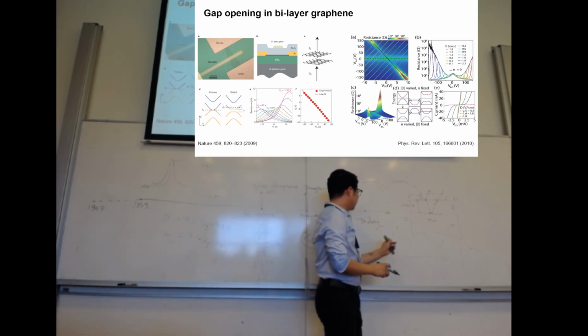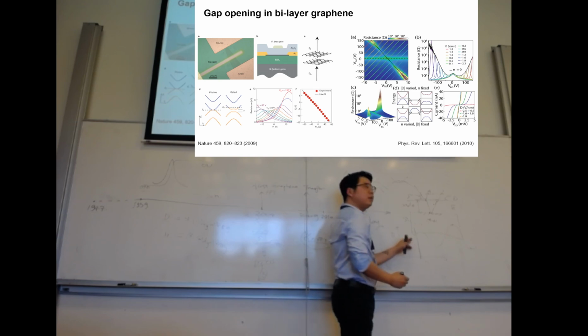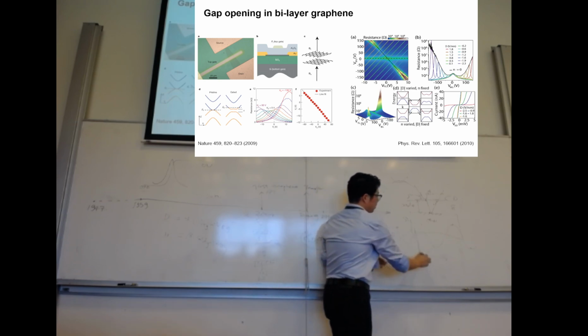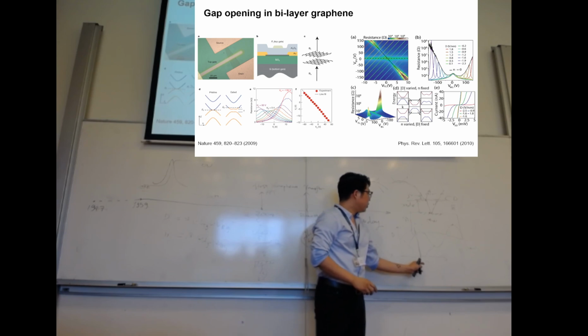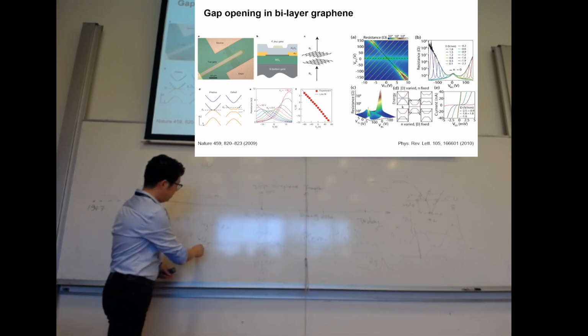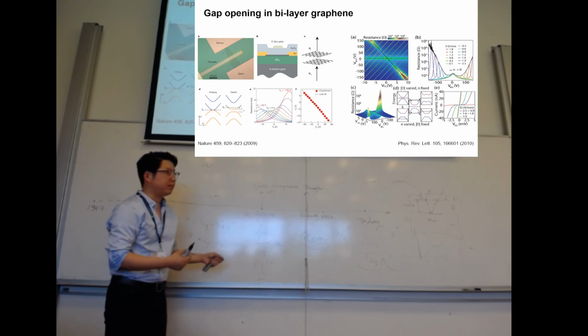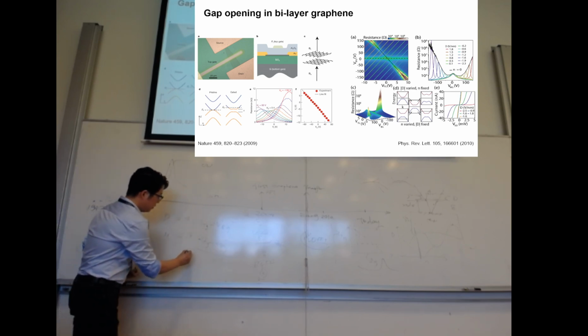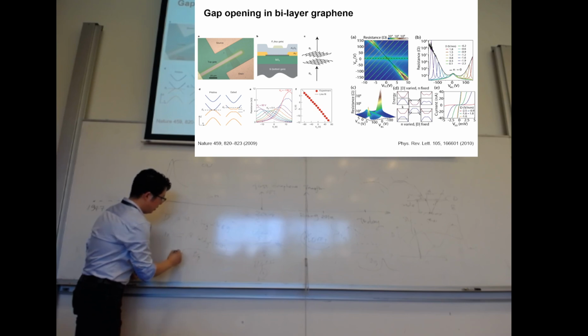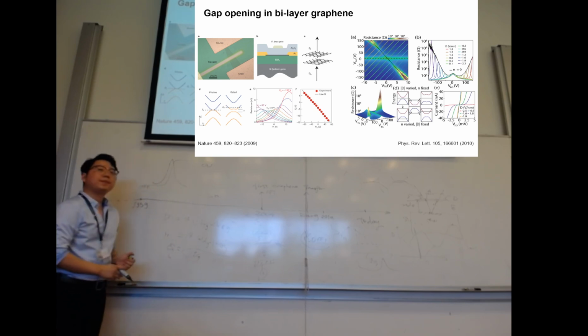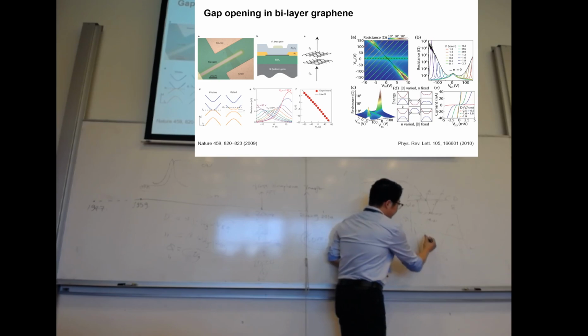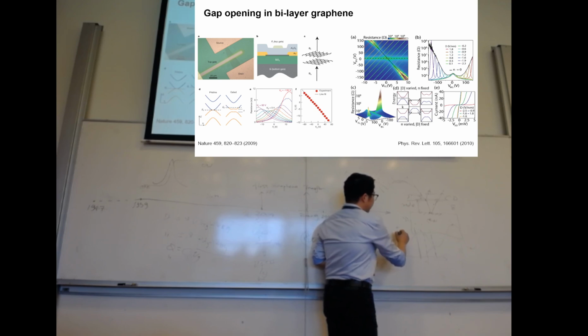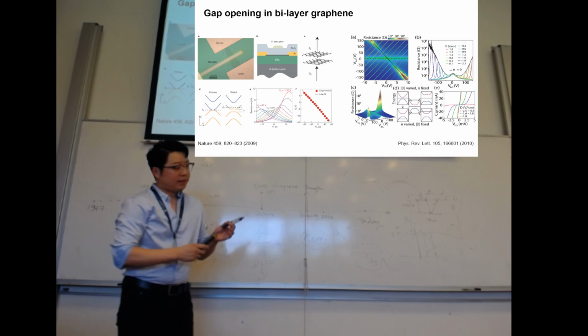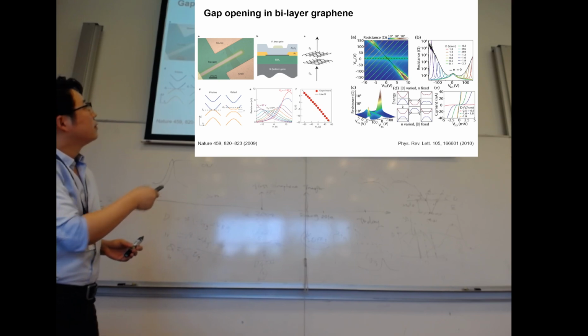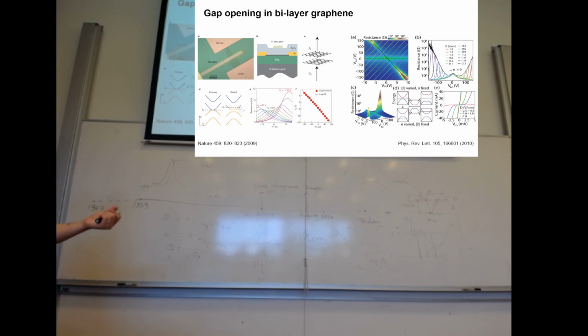If you do that conversion, you will get the resistance peak lying vertically there. So this map will be just linearly transformed. That means everywhere you are sweeping along this axis of n, which is a sum of two gate voltages. That's a sum of two carrier densities, right? Because we linearly convert into carrier densities. It's just capacitance times Vg is equal to Q, right? So Q is carrier density. And everywhere on this axis, you have the same constantly doped carrier density. Everywhere on this axis, you have a constant electrical field. That's why they have lines this way. So it's just current by the capacitance? Yes, it's just a simple capacitance coupling. Nothing big deal.